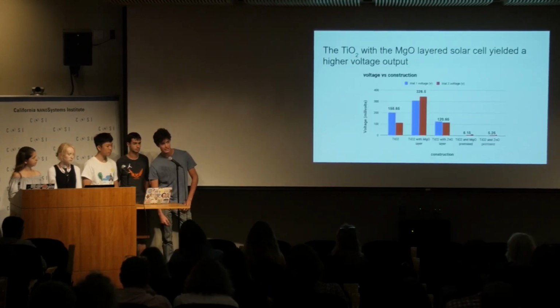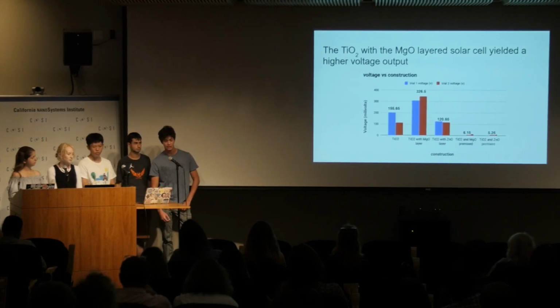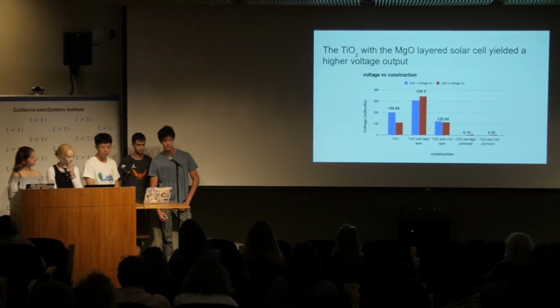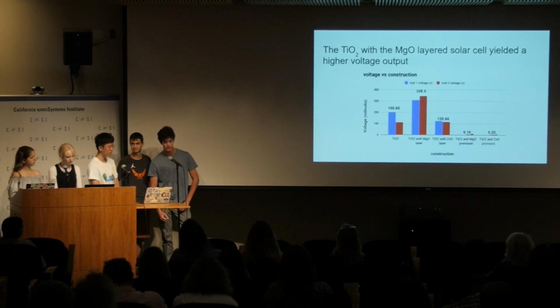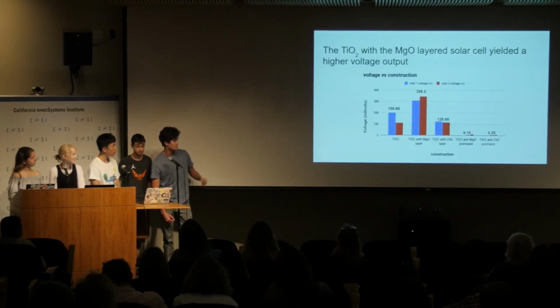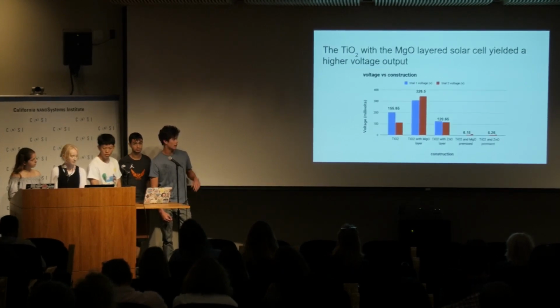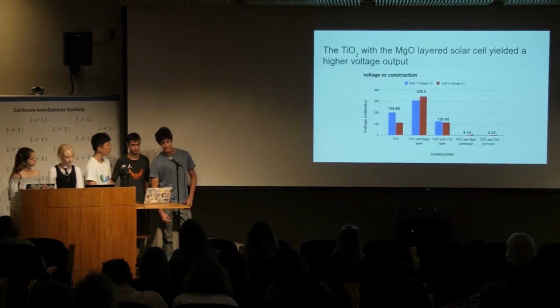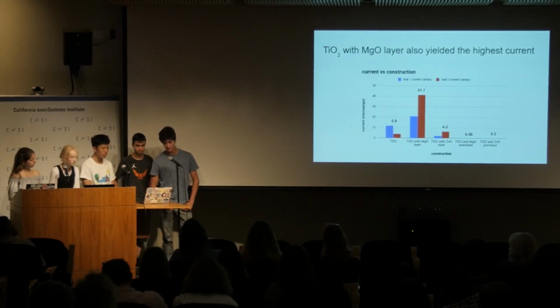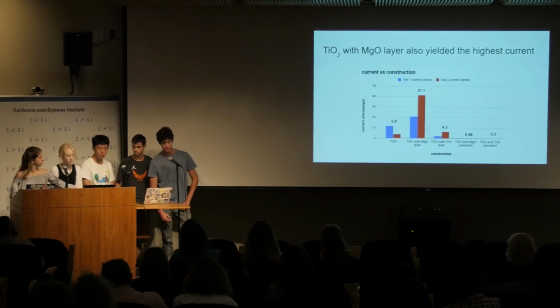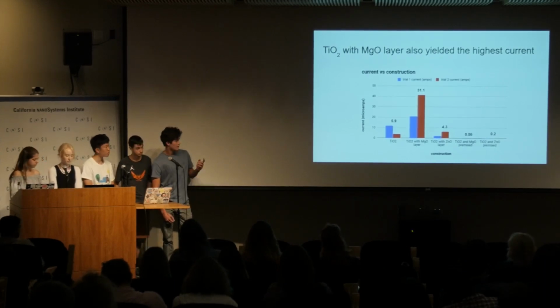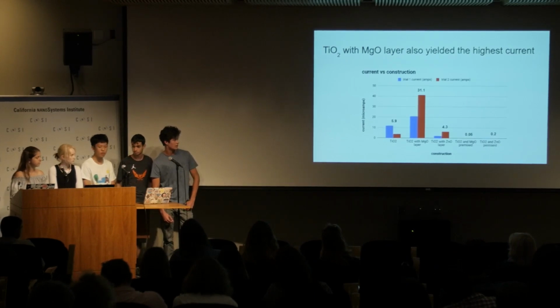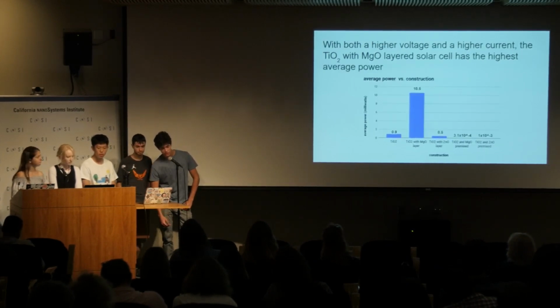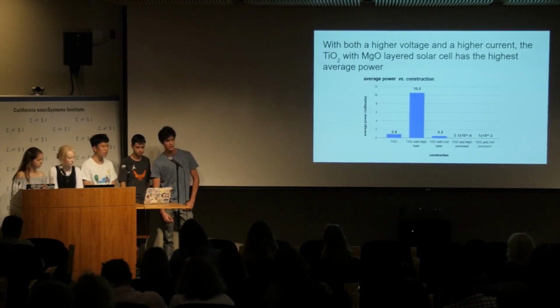So after recording our data with the multimeter, you can see that the TiO2 with the MgO layer is significantly higher. It has a higher voltage output, and it's almost twice the control, which is the TiO2. Also, you can see that the TiO2 with the ZnO layer is slightly lower in voltage output than the TiO2 by itself. And there's basically the same trend for the current, and yeah, the TiO2 with the MgO layer is much higher than the other 2. And also the 2 pre-mixed have little to no current and voltage.